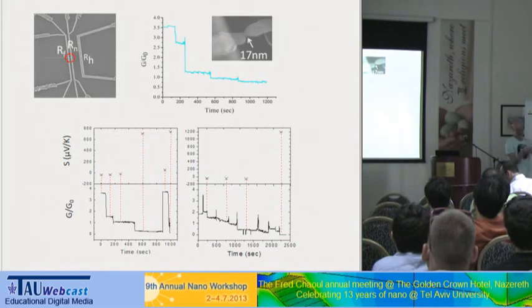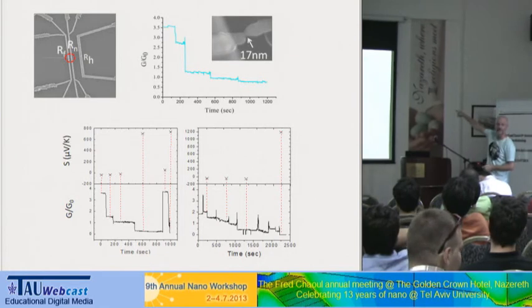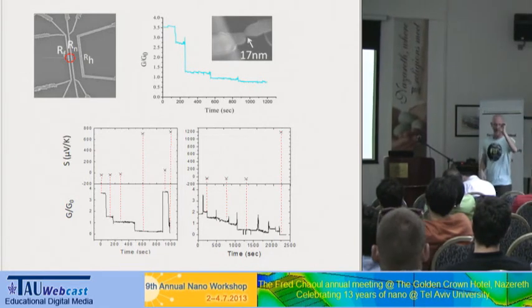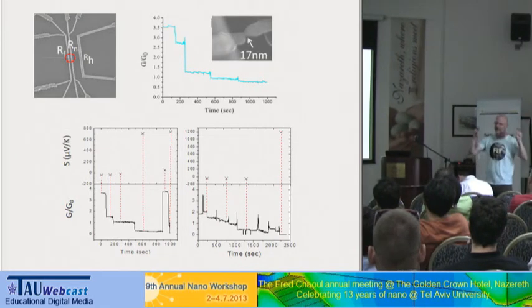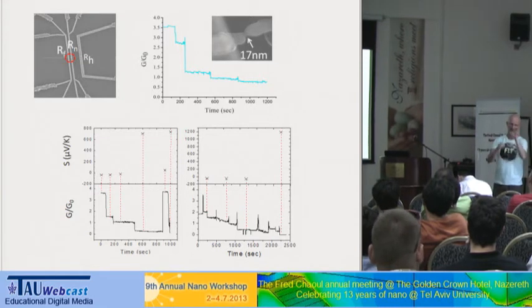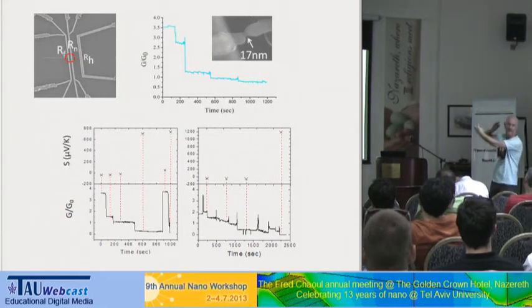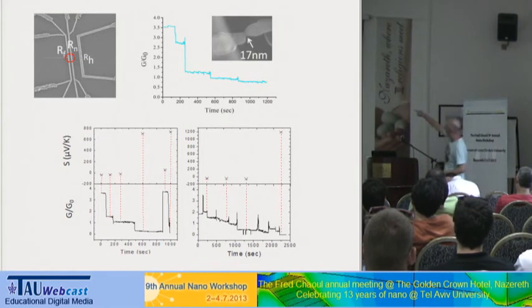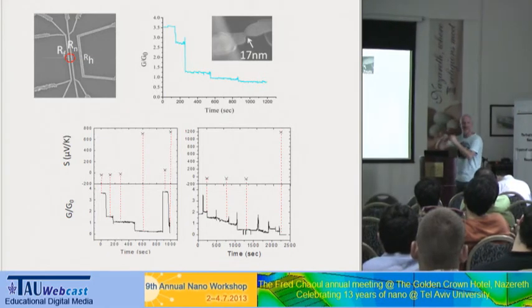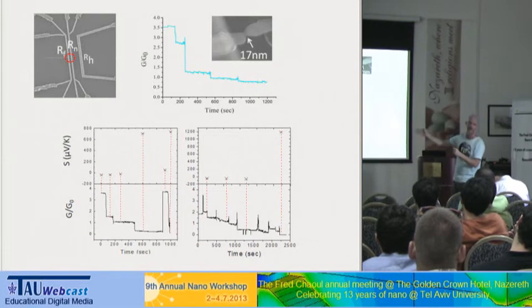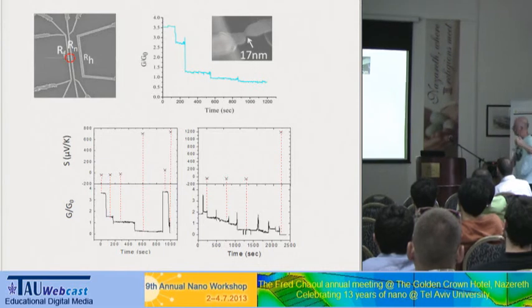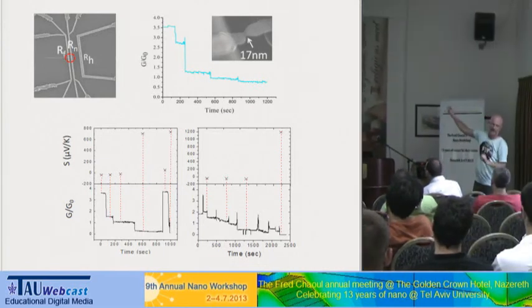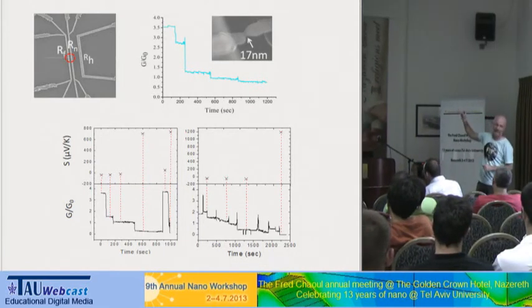So the wire has, once you make the wire, you have one conductor. But then you shrink it. So you have a method by electromigration process that makes this bow-tie shape, and you can change its conductance. So you can actually follow the process, and as you shrink it, the conductance is going down, and you can reverse the process. So we can stop whatever we like. I mean, tell me the conductance that you want to measure, and I can stop.